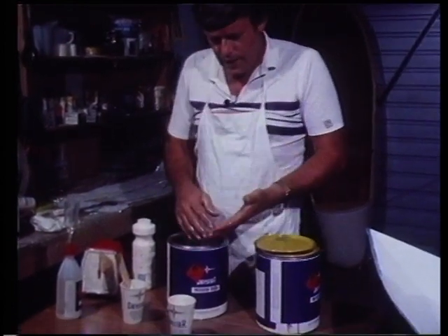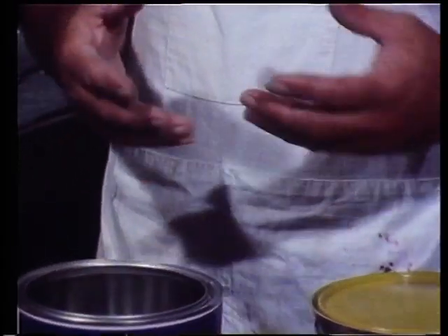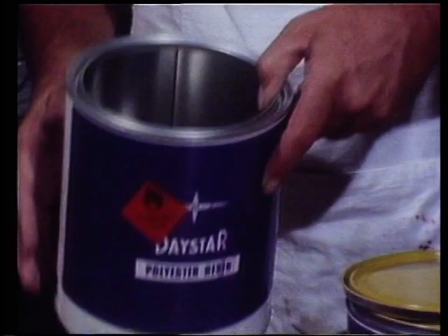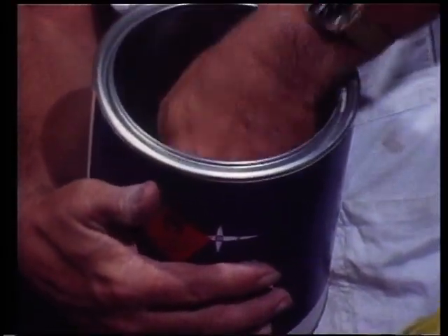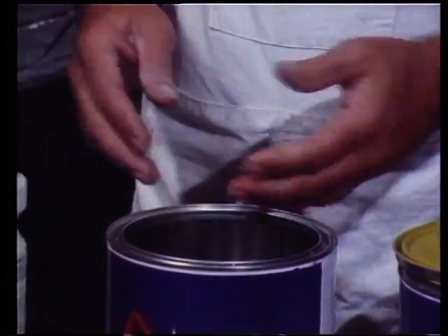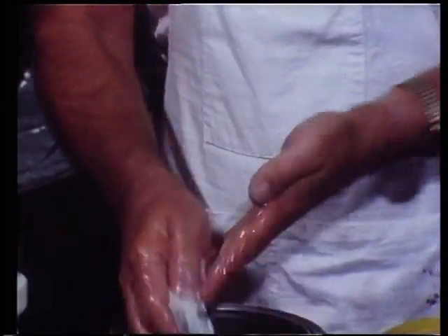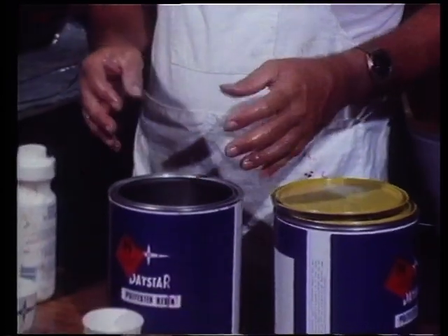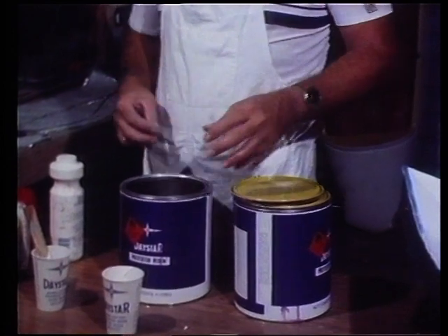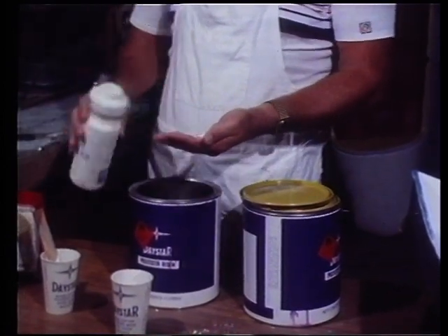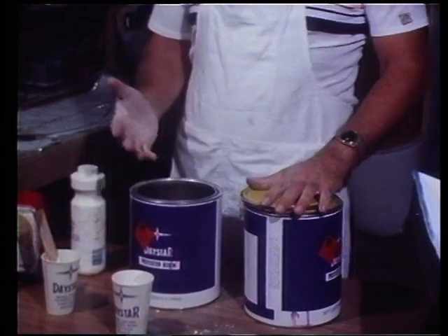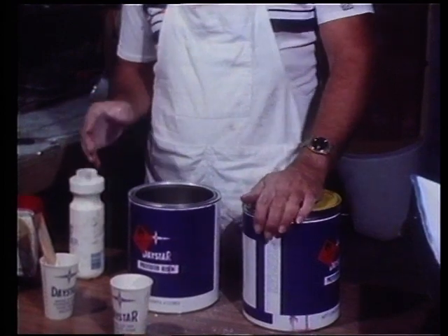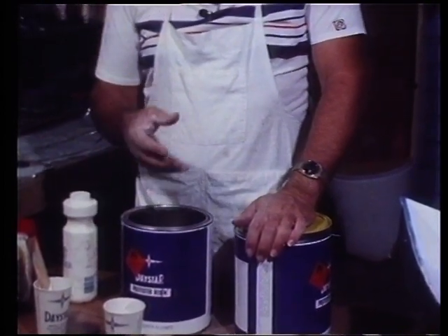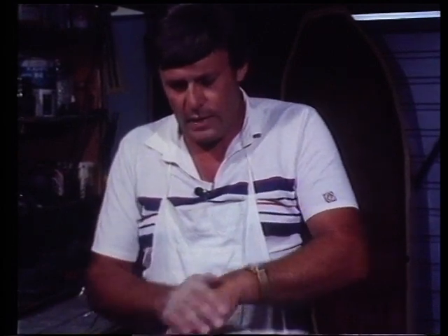So if you wash your hands in it, it will leave a layer of sticky resin on your hands, making them most uncomfortable. So you have a second can full of relatively clean acetone, and I don't know if I can show it to you there. I'll try to. It's a clear liquid which looks very much like water. You have a second can of clean acetone there in which you wash your hands, and it's a good idea, if you can, to keep a little bit of rag in it so that that facilitates washing your hands. Now again, after you've washed your hands in that a few times, it'll get a little bit of resin in it and they'll be sticky. So I always have a shaker of talc, in this case raw talc, and I just shake some onto my hands, dust them over, and it takes the stickiness away and makes them far more comfortable to use. Now I haven't struck many people who are allergic to either the styrene in the resin or gel coat or the acetone, but some people do have a reaction, and it can cause nasty skin ailments there.